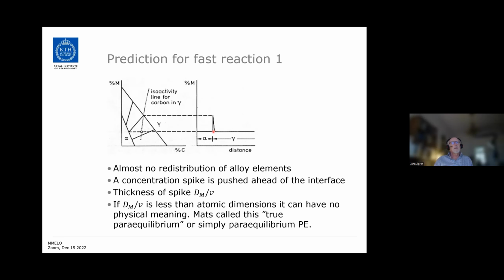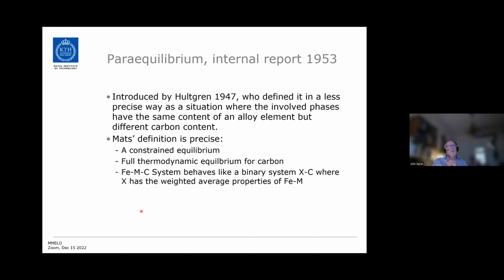Mats estimated the thickness of that spike, and it turns out to be the diffusion coefficient of the substitutional element divided by the velocity of the interface. Now, if this is much smaller than atomic dimensions, Mats argued that it could have no physical meaning. And he called this true para-equilibrium, or later simply para-equilibrium. Para-equilibrium, and this is discussed now in a report, an internal report from 1953.